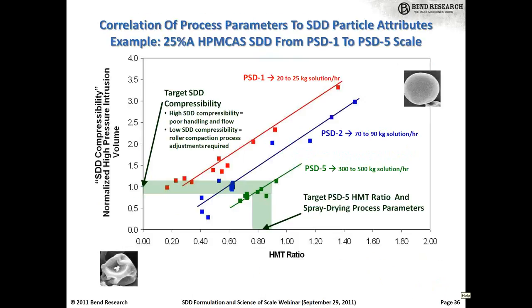So shown on slide 36, we're showing the HMT ratio plotted against the SDD compressibility or mercury intrusion value. And again, the HMT ratio is evaluated considering all of those key thermodynamic spray drying parameters that we've been discussing. So you can think of it a bit as a fingerprint of the spray drying process. So in this particular case, we had a target SDD compressibility that we were trying to achieve, and a target range we were trying to achieve.